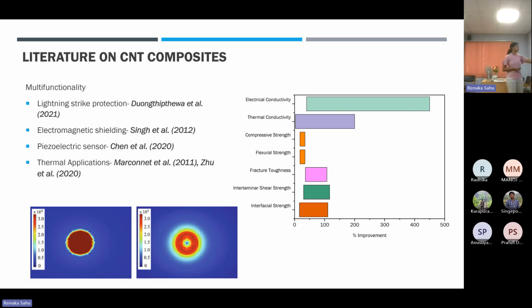This figure shows a normal composite, and a composite with CNTs added. This red zone shows the damage zone due to lightning strike, and this is the one wherein the CNTs are used. So definitely there is much reduction in the damage zone once CNTs are used.